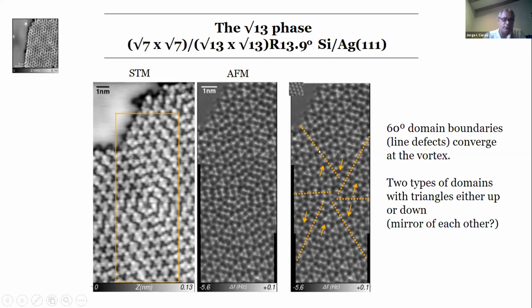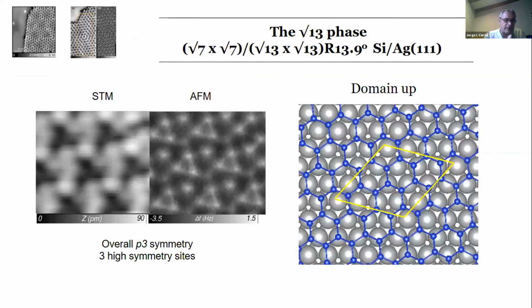So actually, the nature of these two domains is not really well understood. The first thing we could imagine is that they are a mirror of each other. I will try to analyze this. Okay, so we go to the high-res images. This is the STM. This is the AFM. Again, we see these triangles that we typically associate with the hexamers. But we have another two types of bonds. This one here. In the STM images, we only see one of them, but not the other one. It's like a hole. Both images really show you P3 symmetry. And the P3 symmetry can be taken around 3 axes, which are the center of the triangles, or the 2 bumps that we have in the unit cell, either the less bright or the small one.